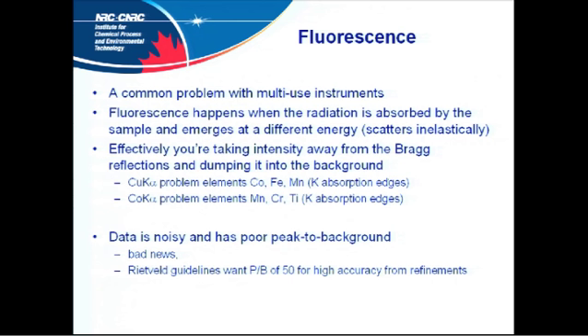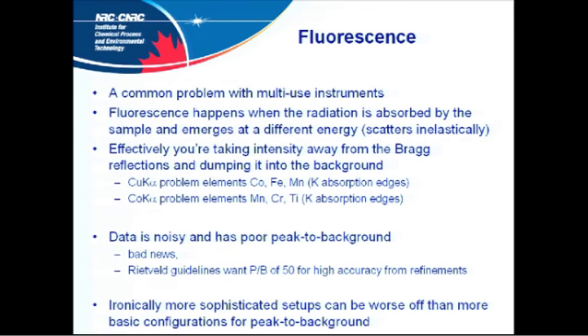A consequence of the fluorescence is you get noisy data and your peak to background suffers really badly, it can be very poor. For anybody who hasn't read the Rietveld refinement guidelines, which Lynn McCusker published, I can't remember how many years ago, he goes into this, and generally speaking, a peak to background of around 50 is desirable for getting particularly accurate results from refinement. For some of the techniques, it might not matter quite so much. And ironically, some of the more modern, sophisticated setups can be more problematic than older instruments.